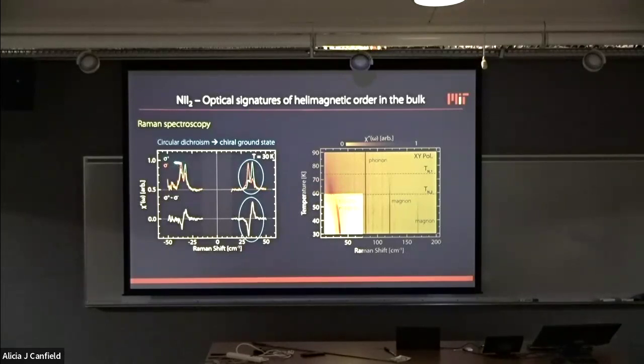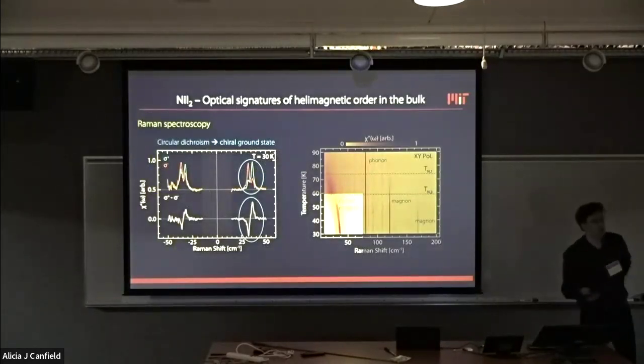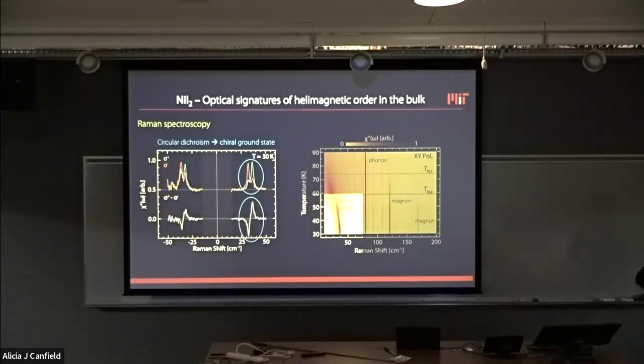What you see is that for circular left and right polarized light, the intensity of this doublet peaks switches, which means that there is a pretty significant Raman circular dichroism of order 70% actually. And we see this both in the Stokes and anti-Stokes, so both in the phonon gain and phonon creation and phonon annihilation side. And our interpretation is this is a signature of chirality. So the circular dichroism of the Raman tells us that the state we're looking at, or the excitation of the state we're looking at, breaks all mirrors.